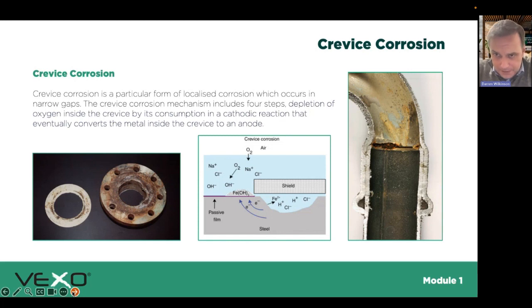And the photograph on the right is some thin wall press fit carbon steel pipe work, which I see nothing wrong with, if I'm honest, in the installation. I think the installer's butted it up nicely, crimped it nicely, but unfortunately there's a gap, there's a crevice, and so thin wall pipe work is quite unforgiving if you don't get your water quality right, particularly carbon steel.